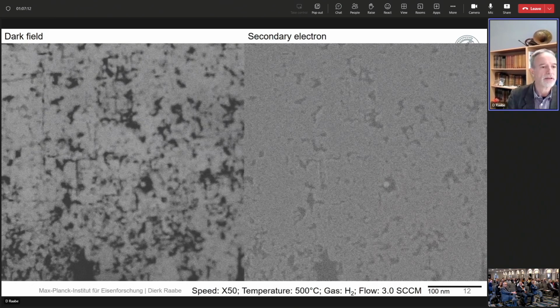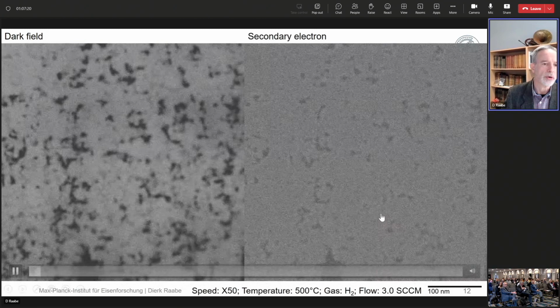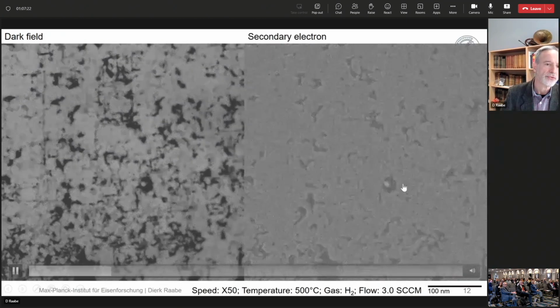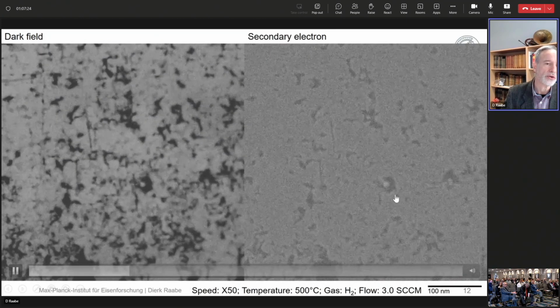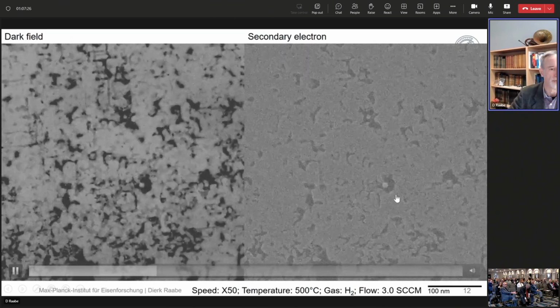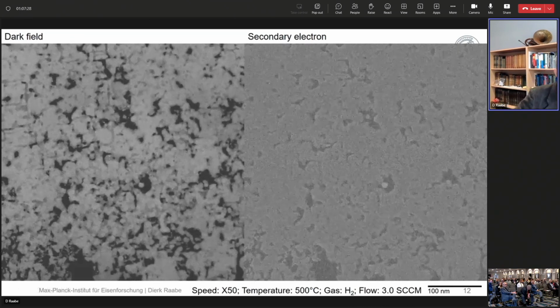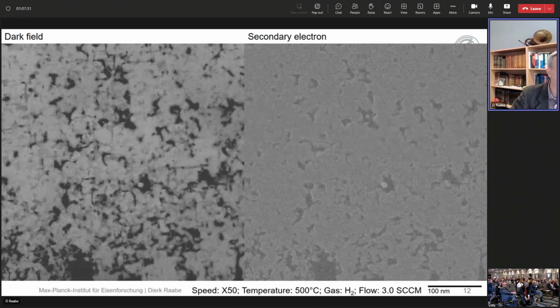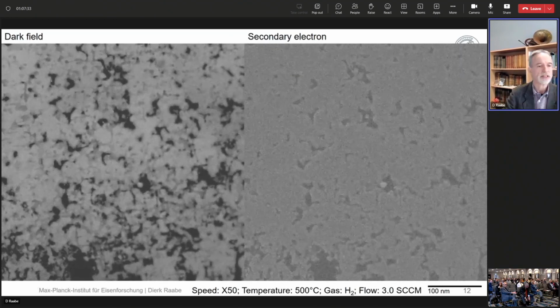And that means when I let this movie run a little bit further, you can see that this is the first iron nucleus growing inside of this free volume, because where the volume is opening up, that means you lost, of course, most of the oxygen through the surface that produces the water, and that's where the iron can be formed.